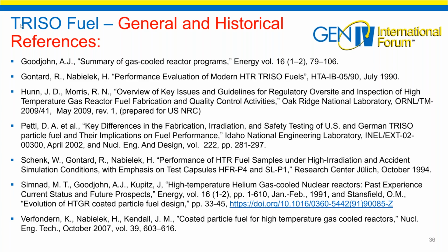There's about 4. The simple one here is, what level of enrichment was used in experiments, and are the results sensitive to the level? Well, in AGR-1, because we are pushing it, we use 19.8. In the reference design for AGR-2 and following, 15% is what we used. And that's adequate for the prismatic block designs. The pebble bed designs go anywhere from 8 to about 12%. So that's why we picked that enrichment. And again, you have a lot of flexibility with a packing fraction up to about 40-some%. Okay, that was a simple question.